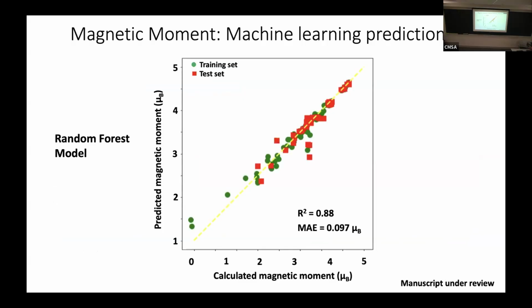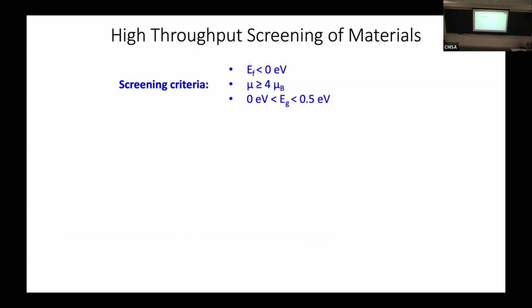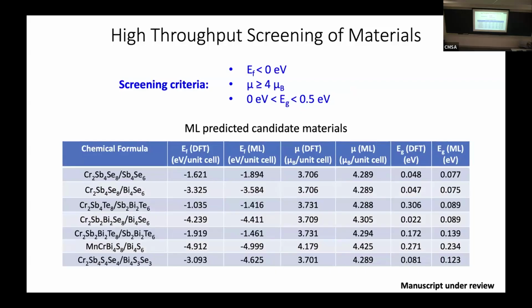If we plot the calculated magnetic moment on the horizontal axis and the machine learning prediction on the vertical axis, again, this gray dashed line as a guide to the eye, we can find that our model is working pretty well because all the points for both training and test data are falling close to this line. So we can again do some screening, selecting some search criteria, using the model to really quickly estimate the properties of a vast set of different heterostructures to find those that are interesting for us, and then check the values with additional DFT calculations. We found that it worked pretty well for the materials we were interested in, which is really nice.